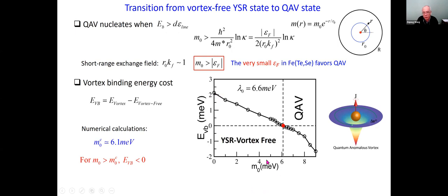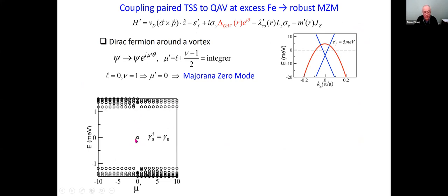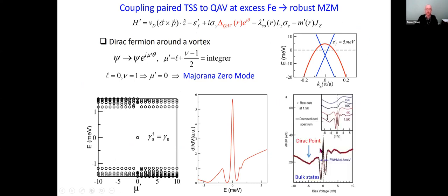We estimate the energy from the binding part, and when binding energy becomes larger than the line energy, you get quantum anomalous vortex nucleation. For short-range exchange field, all you need is the exchange coupling to be greater than the Fermi energy. The very small Fermi energy of 4.5 meV in FeTeSe is what favors the quantum anomalous vortex. The complete numerical calculation plots the binding energy as a function of the exchange field: on one side you have the Yu-Shiba vortex-free state, but when exchange coupling becomes larger than the Fermi energy you have spontaneous quantum anomalous vortex nucleation — a transition from Yu-Shiba states to a vortex state. Once you have the vortex and couple it to the superconducting topological surface state, you get the extra Berry phase, the zero mode, and integer-quantized core states. The core states are cleared from the vortex core, giving rise to a very robust zero energy peak that compares very well to Shuhan's experiment.